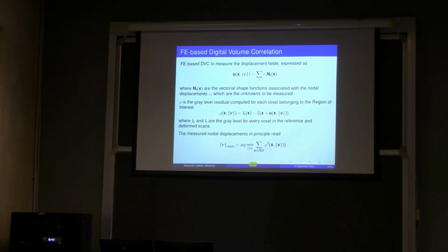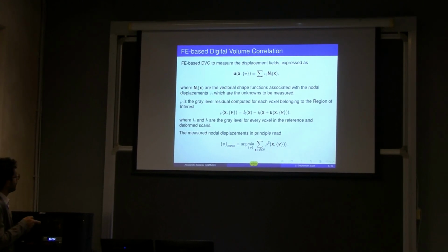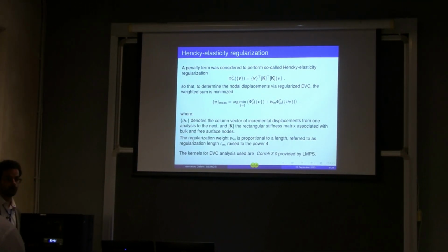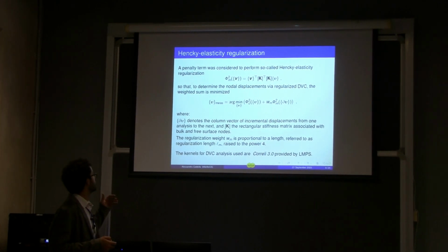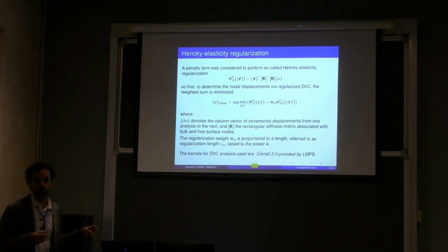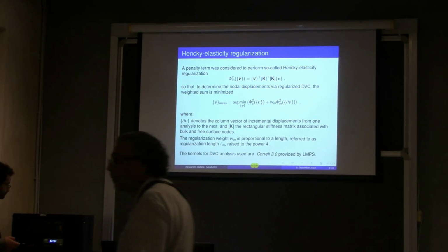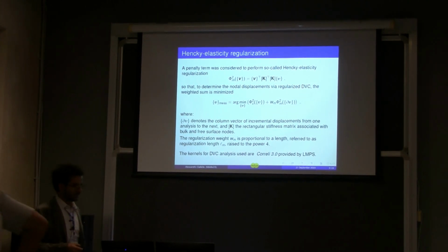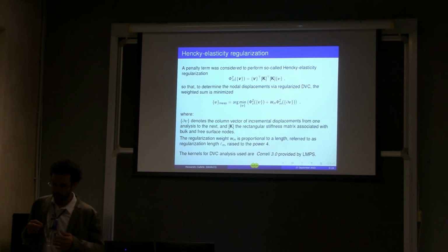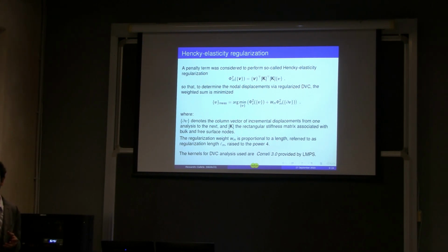Actually, this is not all, because for these cases we needed to add a penalty term to perform the so-called Hencky-elasticity regularization. So we had to penalize the displacements that require too high a concentration of elastic energy.